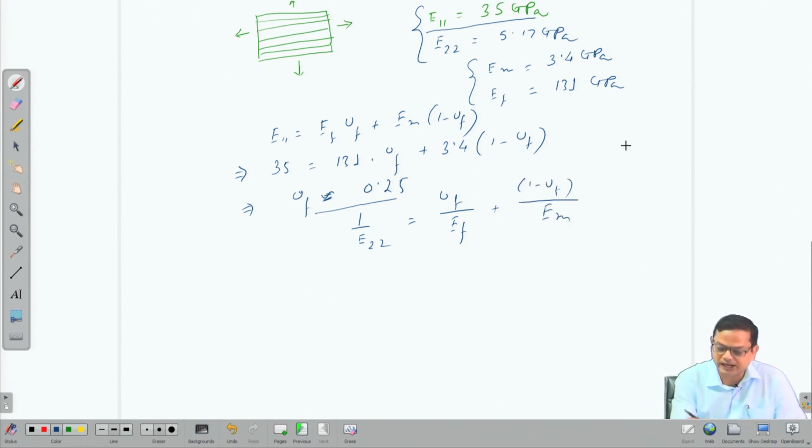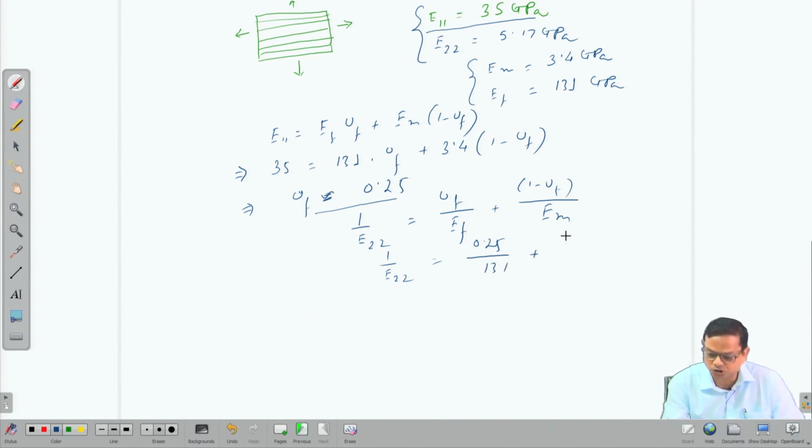So, 1 over E22 equals 0.25 over 131 plus 0.75 over 3.4. From here you can find the value of E22.